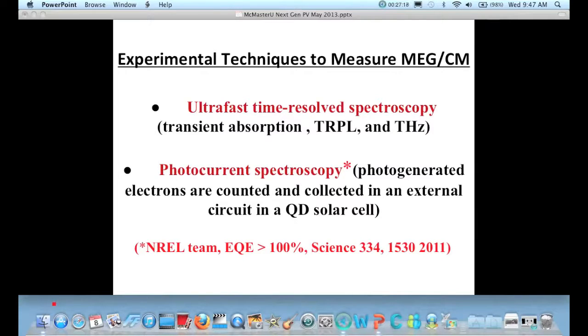And we showed just recently, about 1.5 years ago in this paper in Science, that for the first time in a solar cell, you can measure a photocurrent quantum yield that has a value greater than 100% within the solar spectrum.